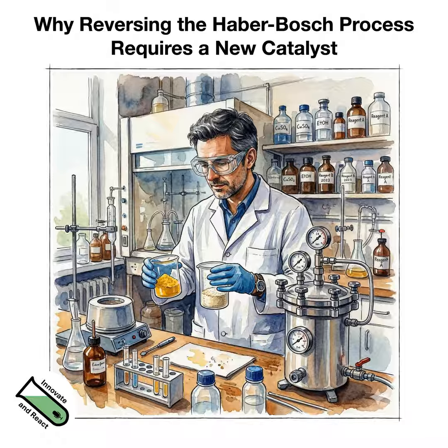It says that the elementary steps of the forward and the backward reactions should be the same, just in the reverse order. And many of those elementary steps have been researched not by feeding nitrogen and hydrogen into whatever reaction chamber, but by feeding ammonia and then looking at the intermediates that you have at the surface. You just approach those intermediates from the other side, and then you get them in a higher coverage compared to if you try to synthesize those from hydrogen and nitrogen, but at maybe too low temperatures and for sure too low pressures.